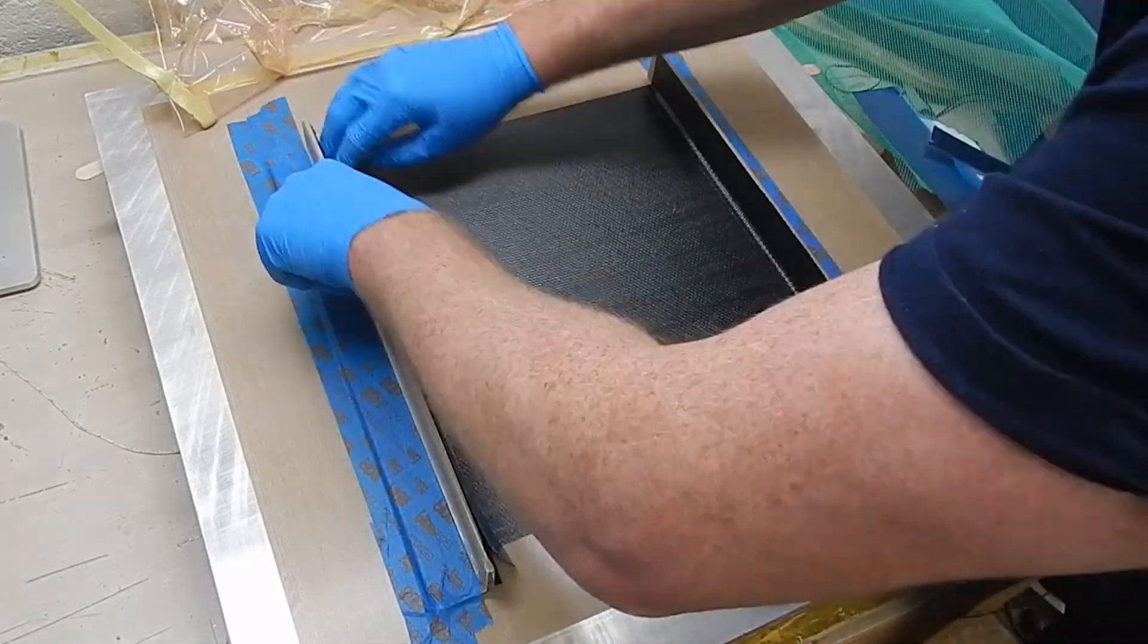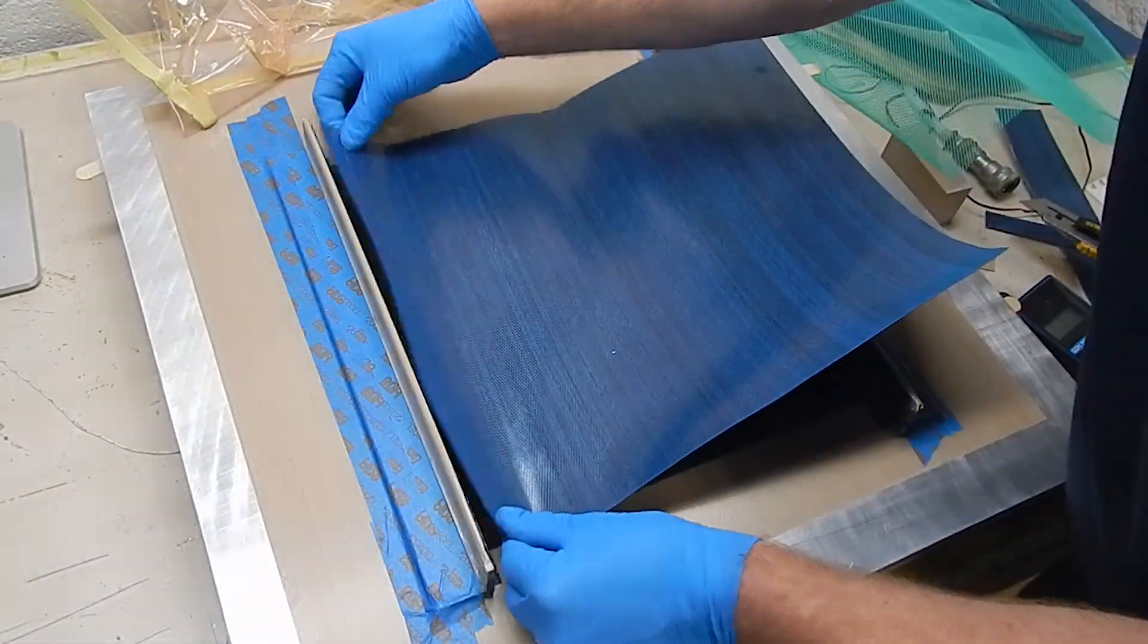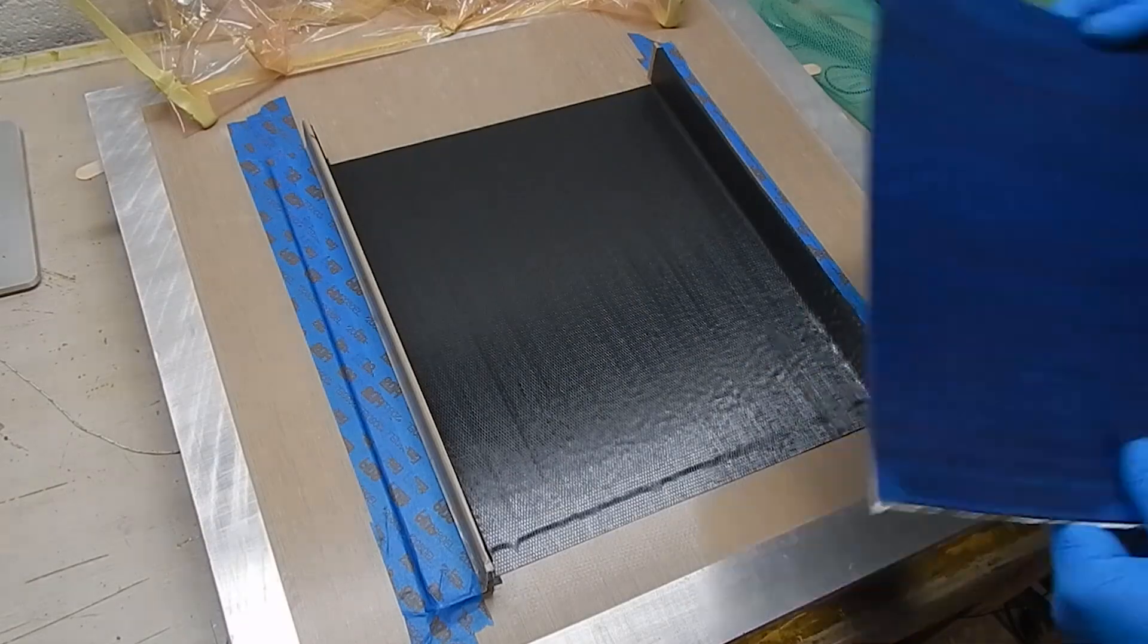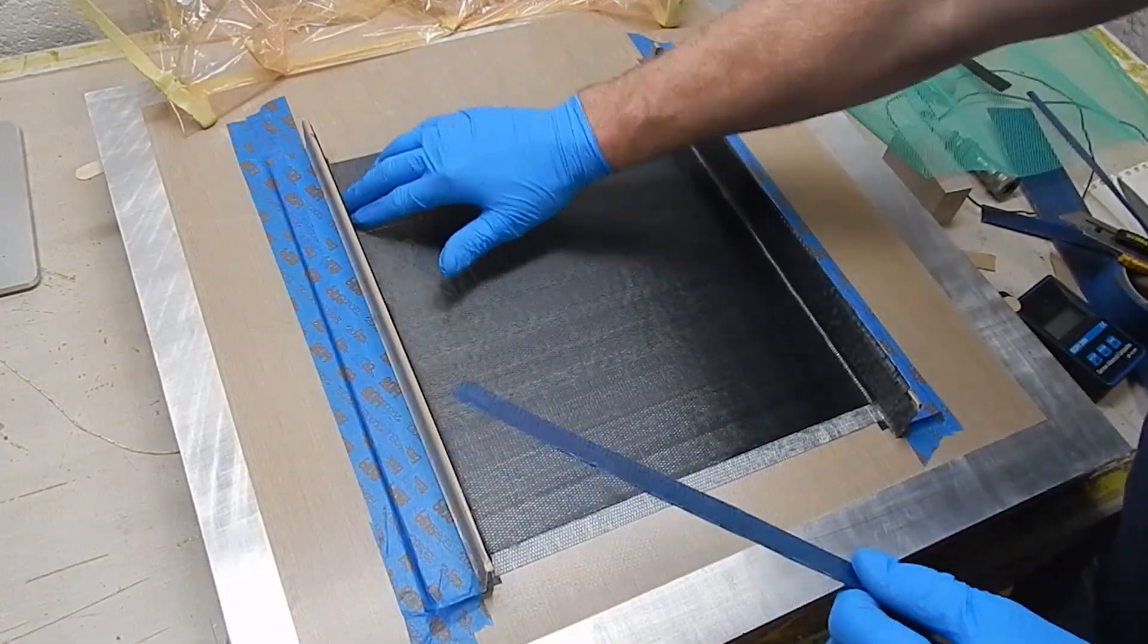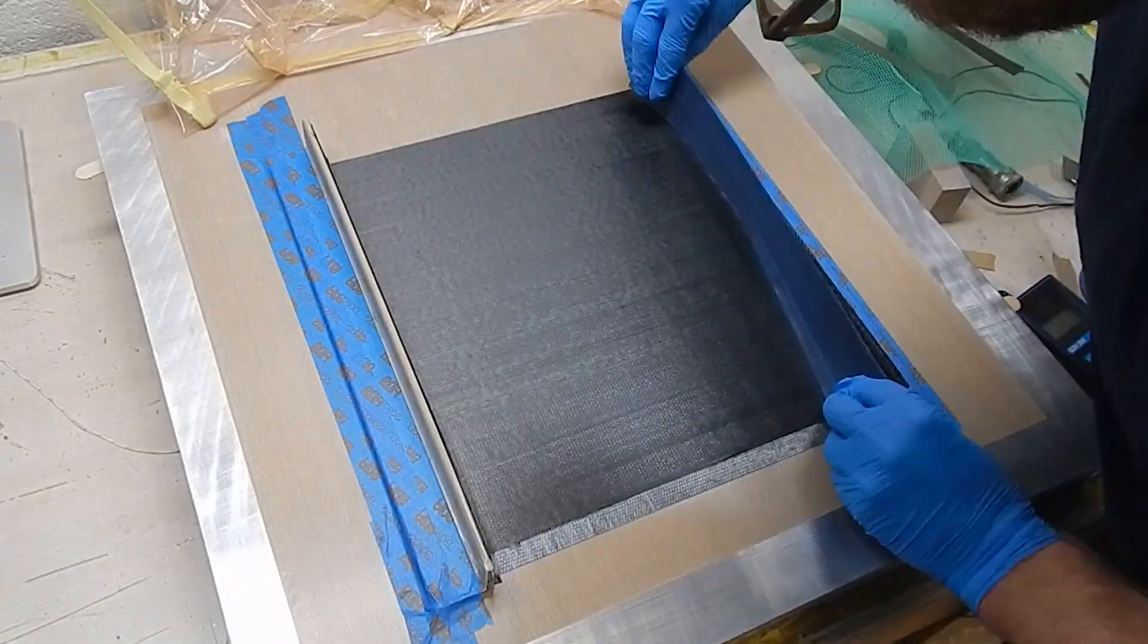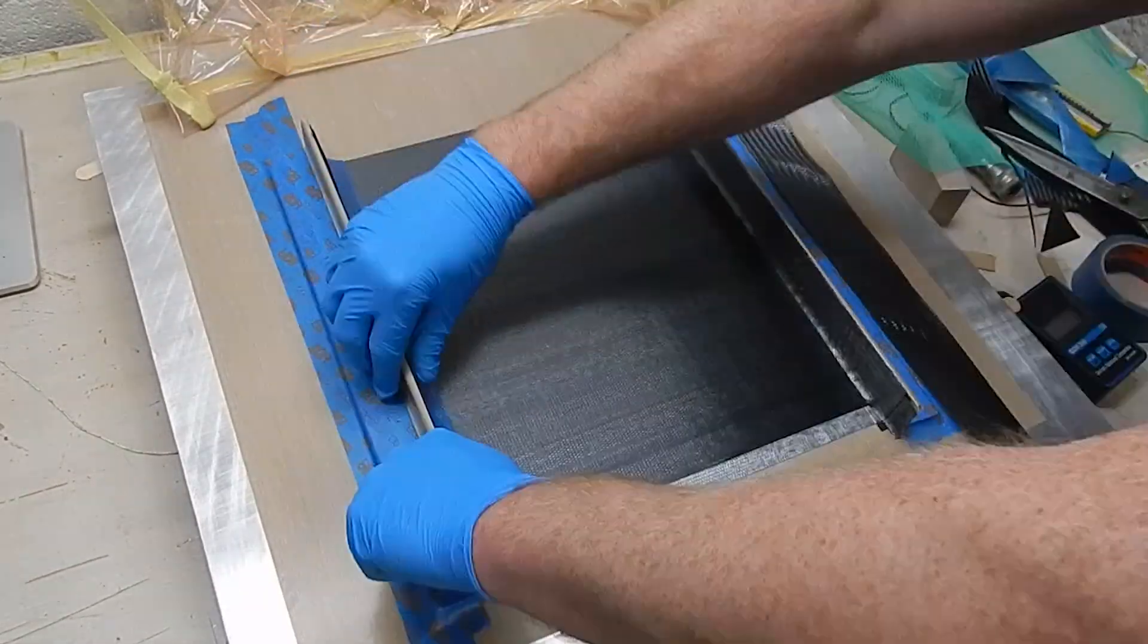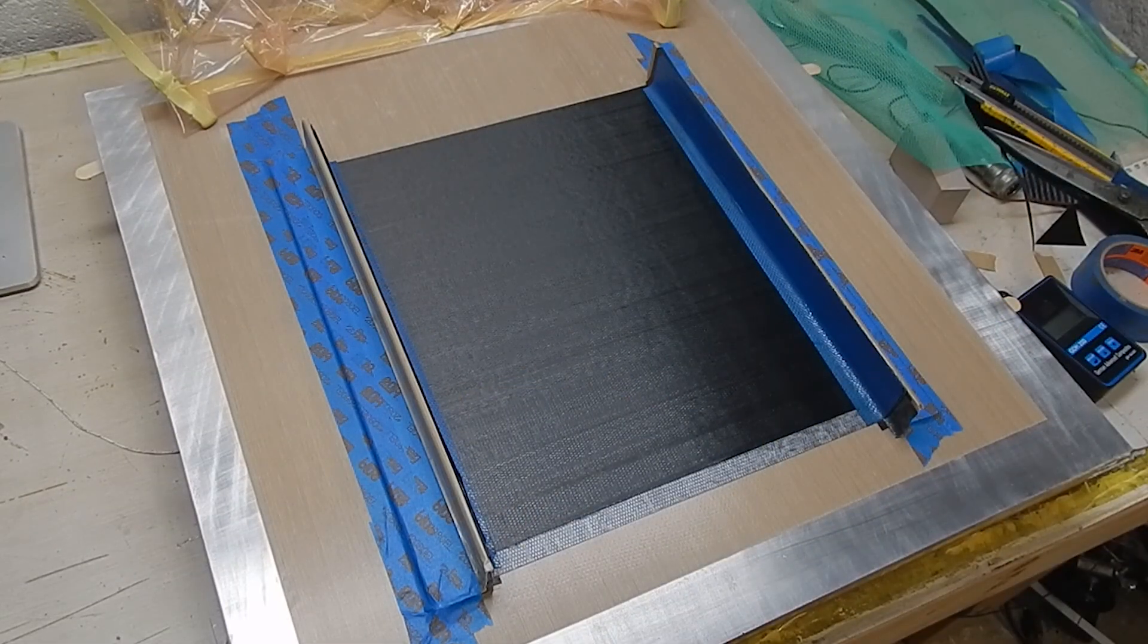Putting two additional strips of uni reinforcement on the flanges in the flange direction. And in the middle, there's this zero ply that because the fiber is going in the direction of the radius, it could just bend right up the flanges. And so here's a second one so that the panel laminate is symmetrical about that middle ply. And here are the two additional pieces of uni. And then to finish it off, another ply of plus or minus 45, 200 gram woven that laps about 10 millimeters down onto the panel itself. And this provides the structure that keeps the flange from just falling off.